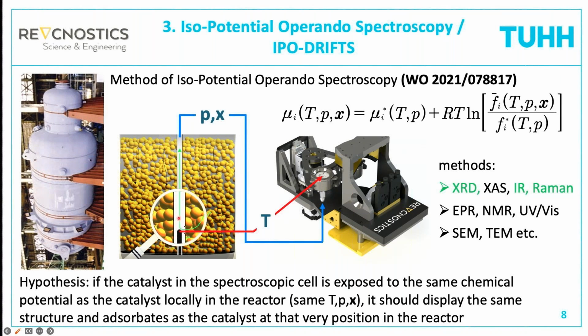So the chemical composition of the reaction mixture, which we denote here with the mole fraction vector X, is fixed, and then it enters the spectroscopic cell. We can design this transfer system in such a way that the pressure drop is very small. Maybe 100 millibar are sufficient to bring the gas over here. And because we measure the temperature locally in the profile reactor, we can now adjust the temperature of the catalyst in the spectroscopic cell to the same value.